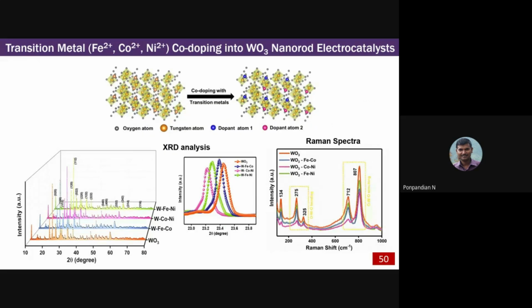Now the next one is the transition metals iron, cobalt and nickel in co-doping: iron and cobalt together, iron and nickel together, cobalt and nickel together. In that way, we are making different electrocatalysts for the applications. When the transition metal is doped into tungsten oxide, the structural property changes. This gives much improved stability in this kind of catalytic material, and in that way we can make a better electrocatalyst.